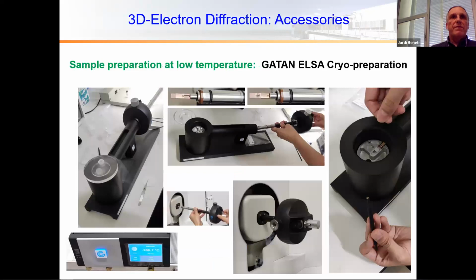Also, we have another device, from the company Gatan, which is the ELSA. ELSA additionally allows you to measure at 100 Kelvin and to cryo-prepare the sample. You have a protected head where the grid comes, and you can introduce this in liquid nitrogen, so you put the sample inside liquid nitrogen and then measure in the system. When you introduce a sample, it's already cooled to 100 Kelvin, and you can immediately start to measure at these temperatures, so that you avoid vacuum and higher temperatures when you do a measurement.